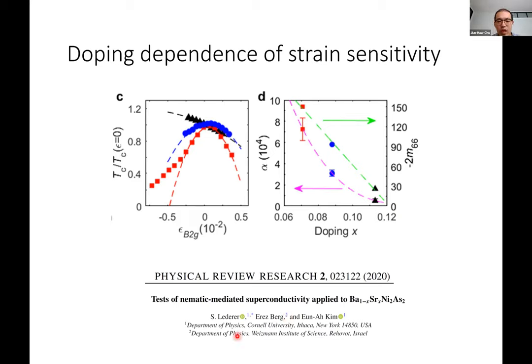And one thing they pointed out is that the strain sensitivity will ultimately be proportional to the nematic susceptibility squared. Therefore, we do expect a stronger doping dependence for strain sensitivity compared to nematic susceptibility. So before I close this section, let me just give a few outlooks. There's actually one more slide.